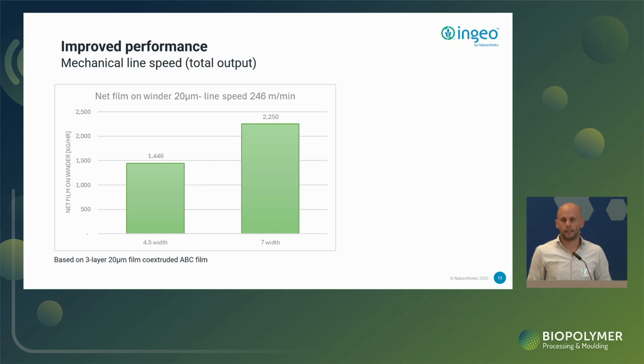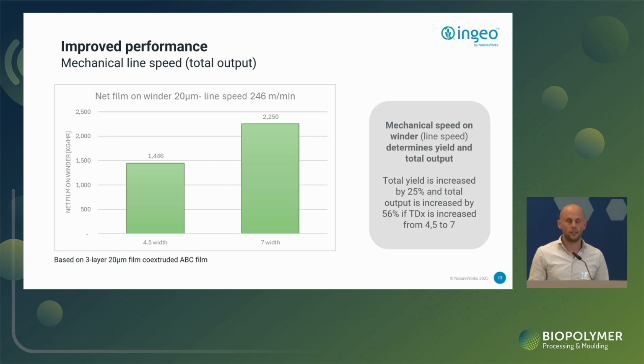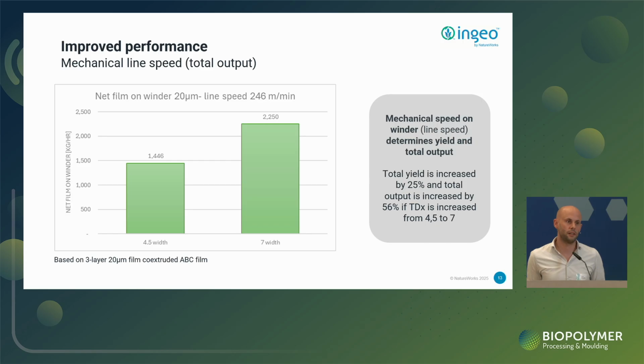This is just a simple example, considering you have a film 20 micron thickness, running at a line speed of 246 meters per minute. And then comparing a 4.5x stretched film versus a 7x stretched film. And you see that the output is increased by 56% due to the higher stretch ratio, which results in a higher width film and therefore increasing the productivity.